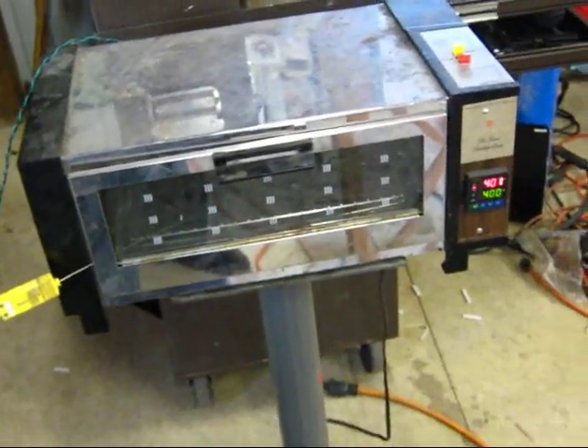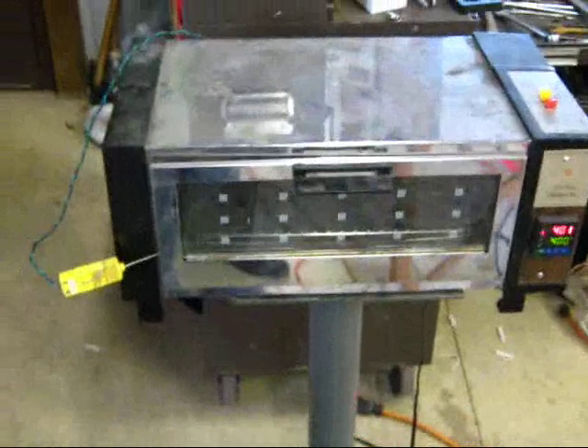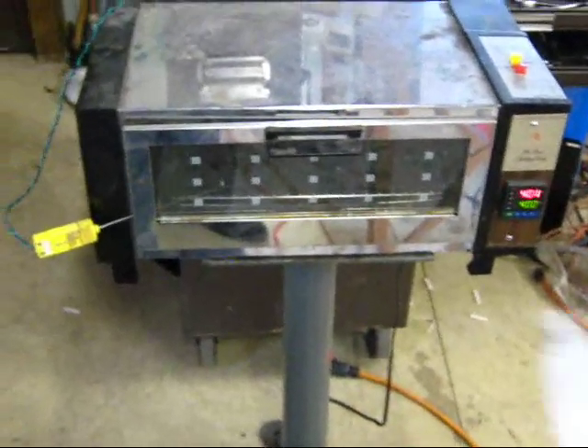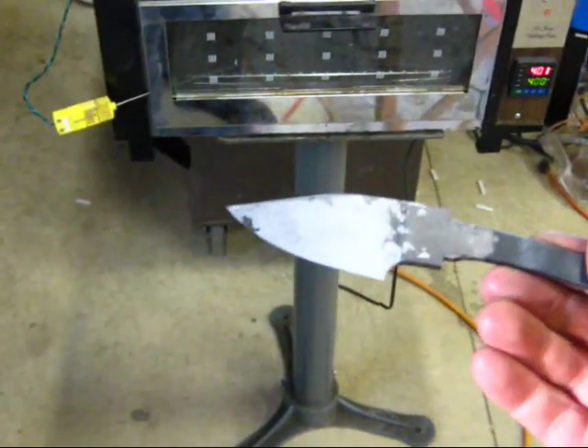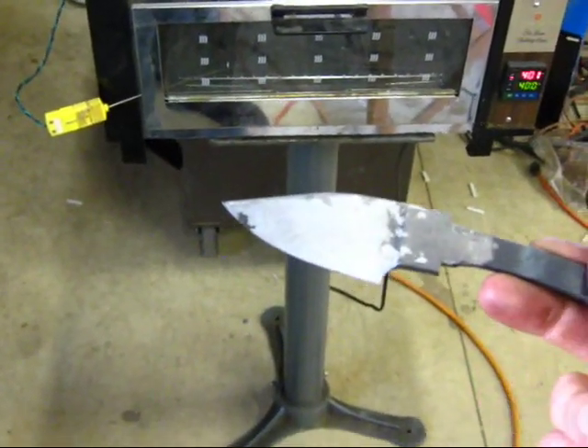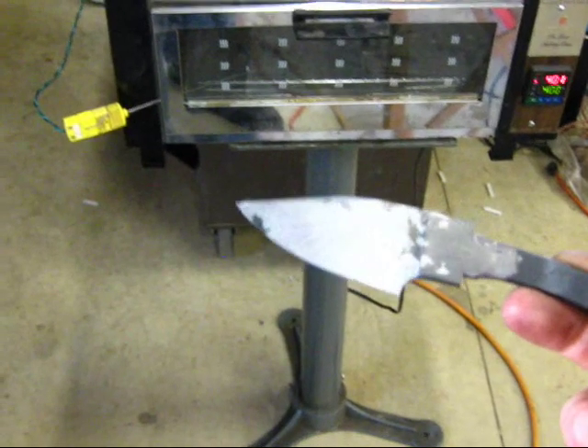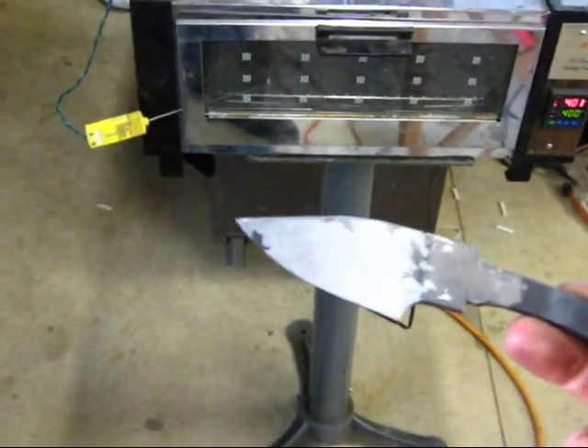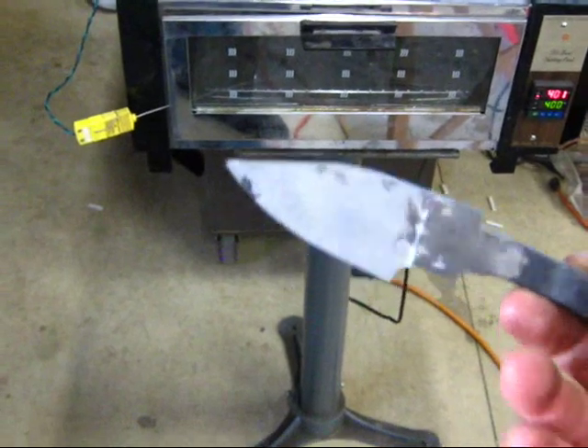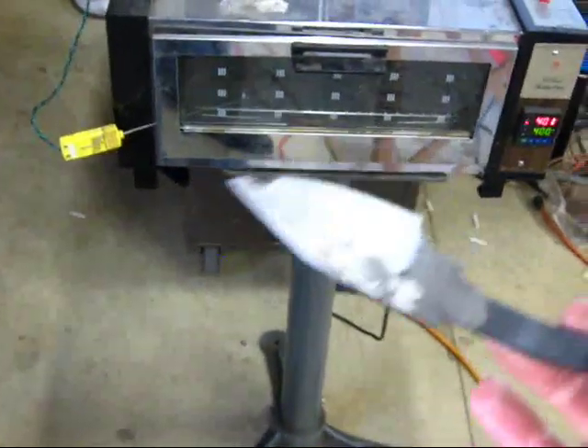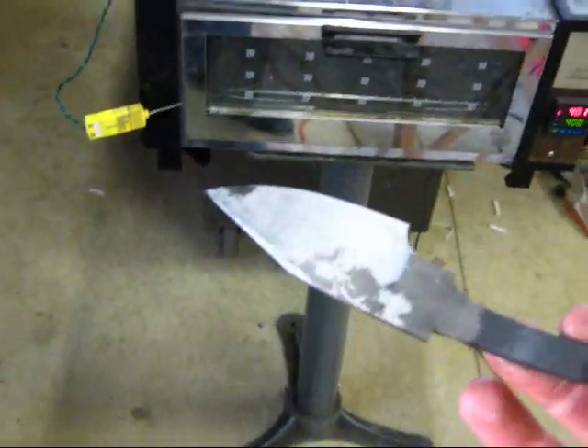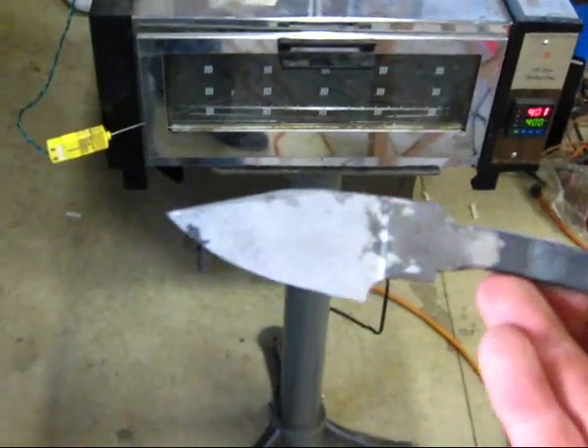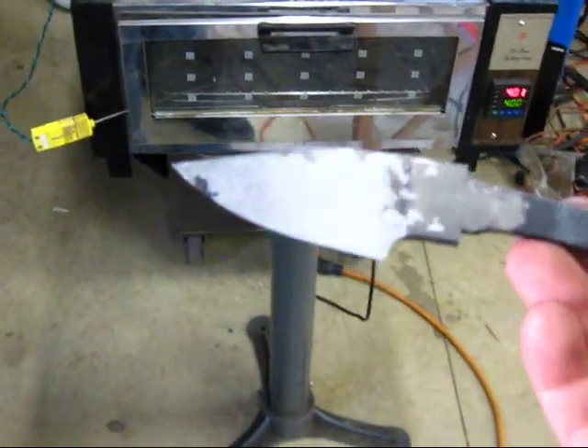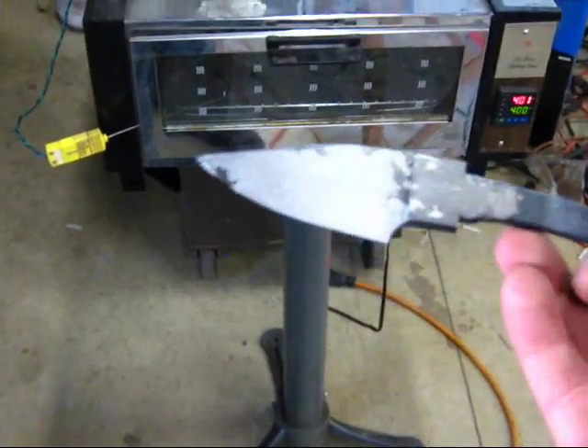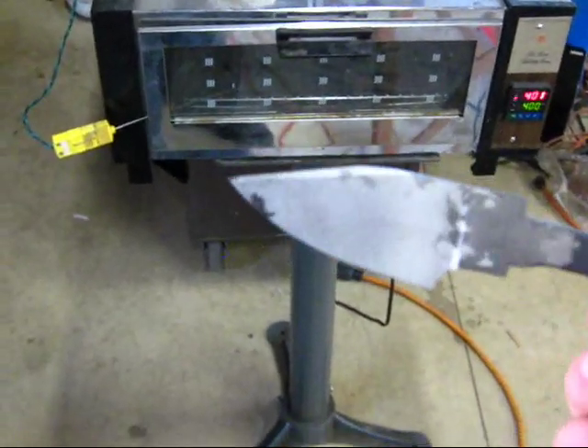So I'm going to go ahead and put the knife that we just hardened, that's in its fully hardened state, in the toaster oven to temper, and I'm going to leave it in there for 2 hours. One hour to ensure that it gets completely up to temperature, and one hour to allow any retained austenite or anything that needs to be fixed within the microstructure of the steel, if you will, to take care of itself, which typically, like I said, takes about an hour.